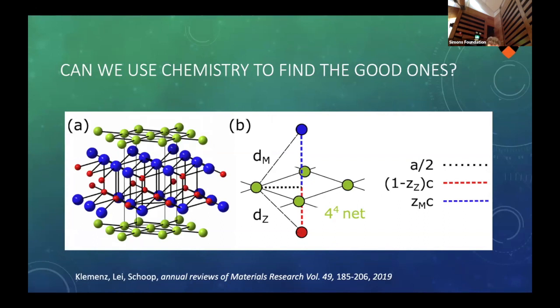You could also view it as, if I want my tight binding model to describe the square net perfectly, then it's better isolated from all the other junk in the crystal structure. So we defined a distance ratio where we said this distance here needs to be shorter than this distance or this distance, whatever here is the shortest.